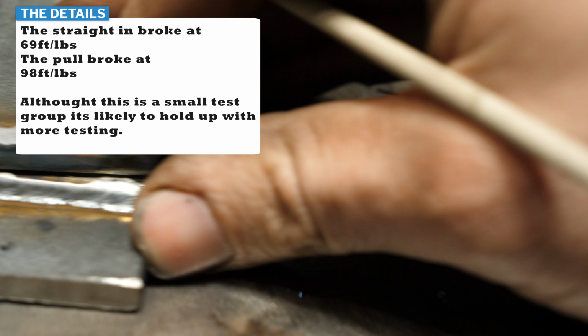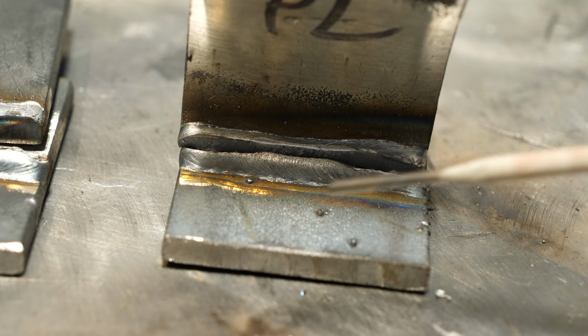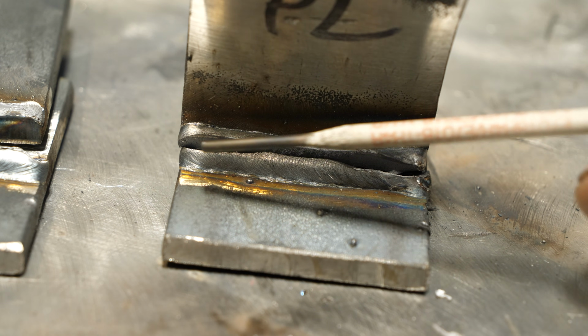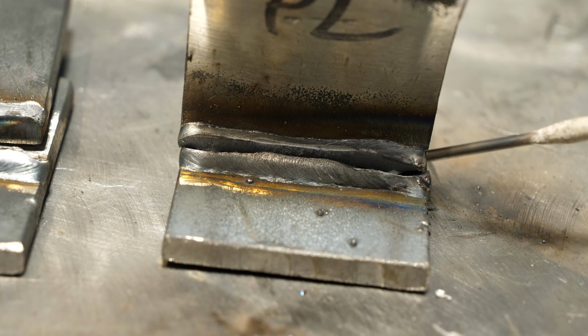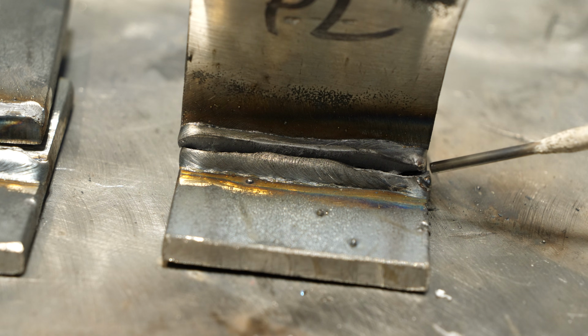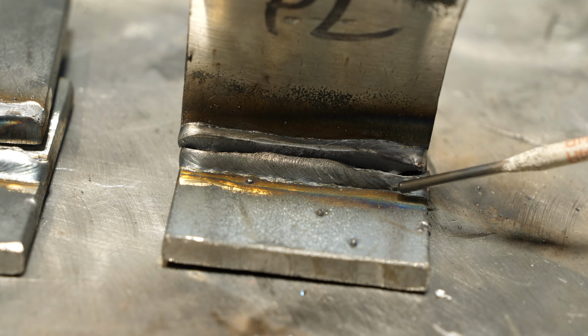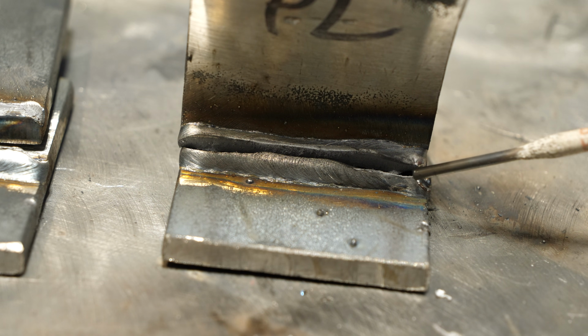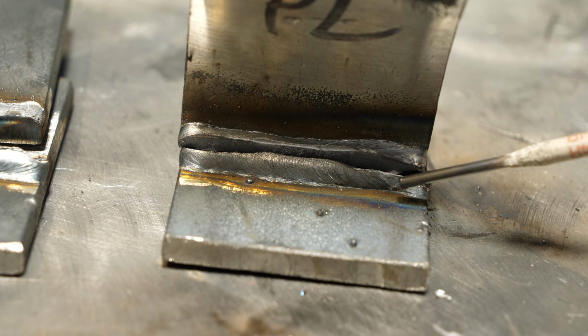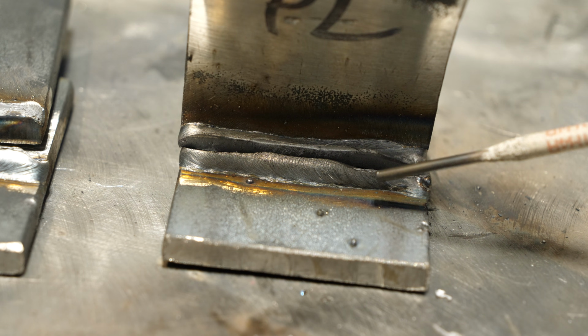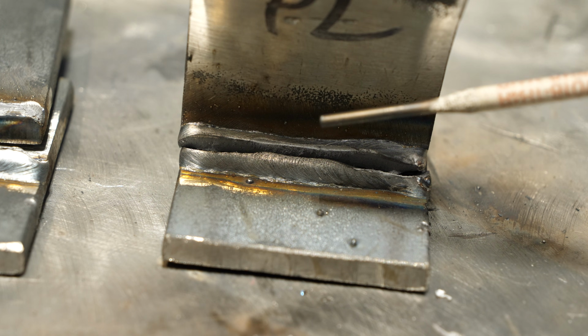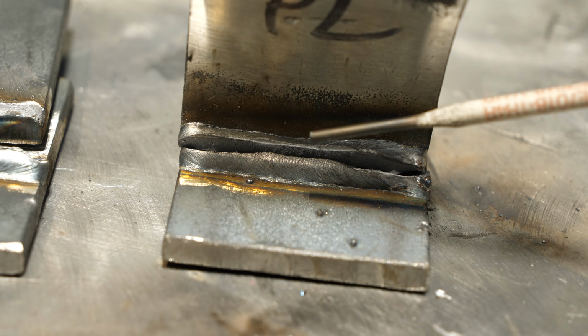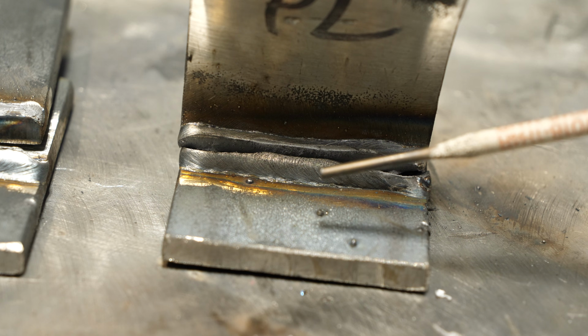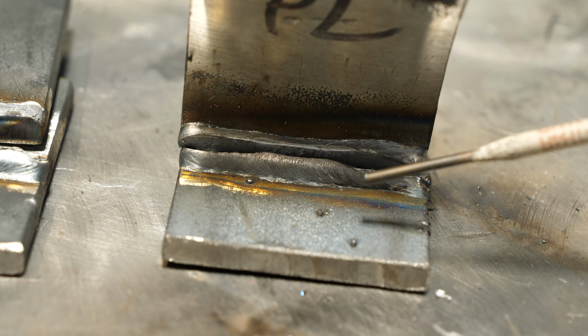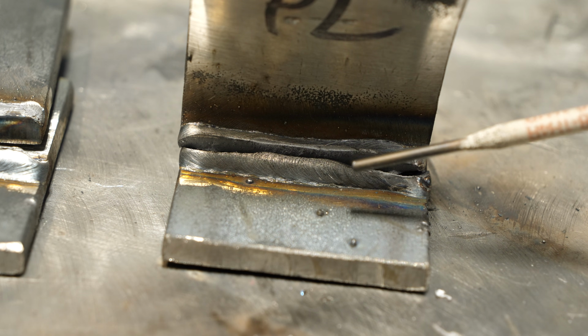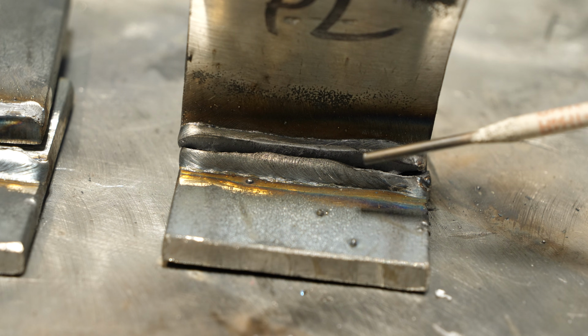Now let's look at the pull. All right, so here's the pull angle. As you can see, the weld broke straight down the middle, which is the most desired result. It is favoring the bottom plate a little bit here, more so than the top plate. It's not bad, but overall a very acceptable result. Now this one took more force than I was able to do because I ran out of room to bend it. I ended up putting it in the shop press to break it the rest of the way because it still was pretty well attached.